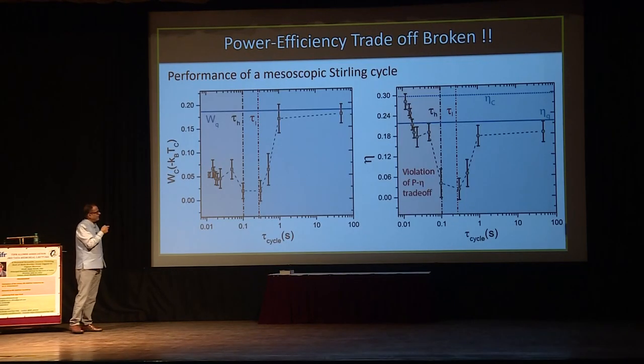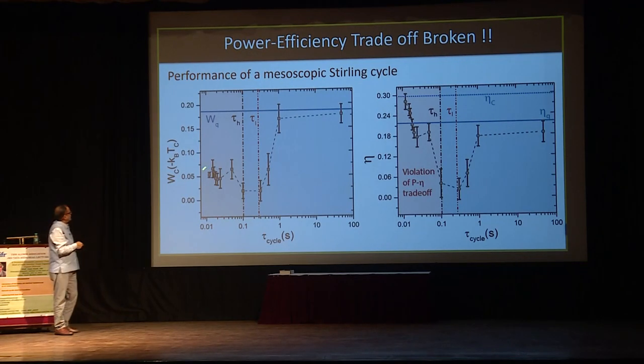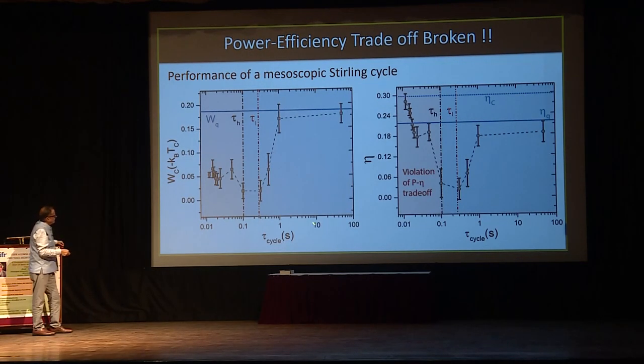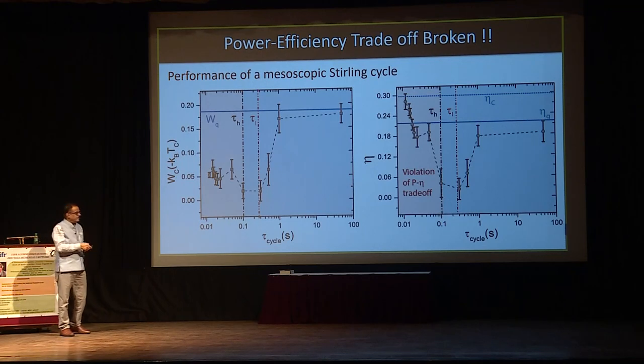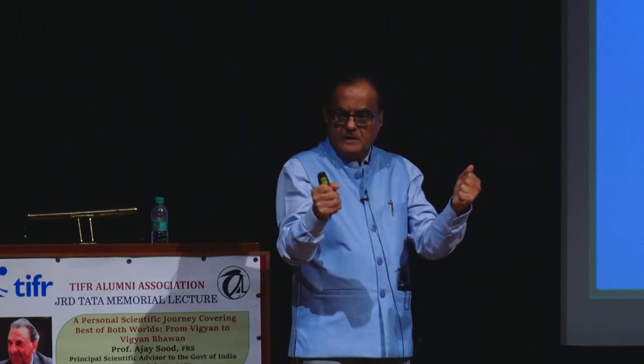So this is the final result, without worrying about the details, you look at the work done. The tau cycle very large, 50 seconds, you have what you call the theoretical limit of the Stirling engine. And as you come down, it is coming down. This is the theoretical expectation. But now, the moment you cross this 100 milliseconds, instead of becoming negative, zero, it's crossing this, it starts going up. You can see the number of data points. And you have a finite work when the engine is moving very, very fast. And we could go up to 10 milliseconds of the cycle time.